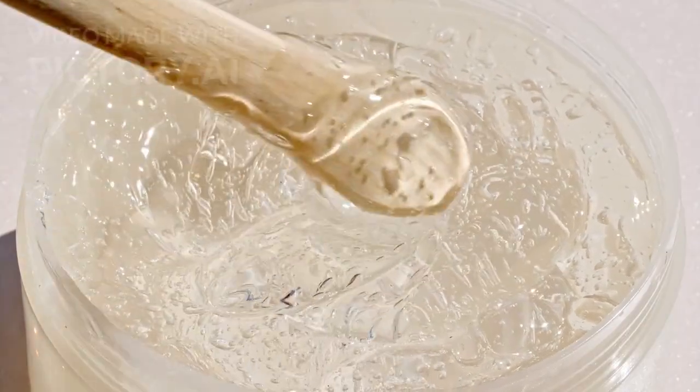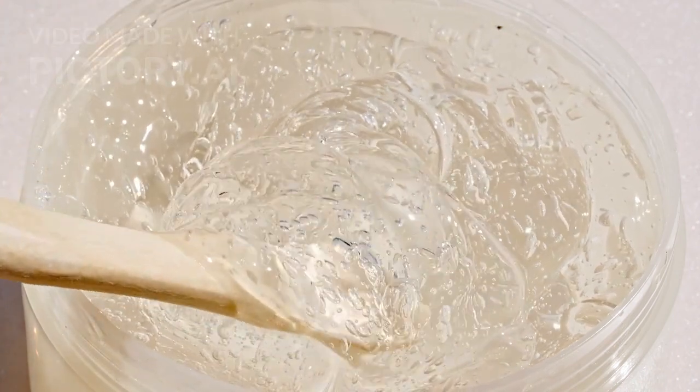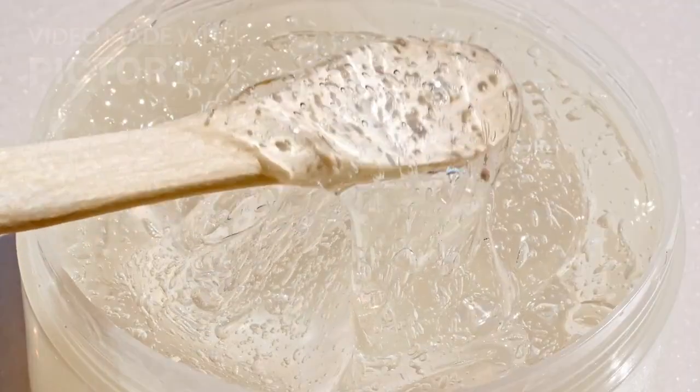Higher temperatures and longer times for that initial heating step, the gelatinization, were really important, and they found something quite clever about drying it. Fully drying the material after making the paste didn't hurt the strength. And then slightly rehydrating it just before the final compression step actually helped.